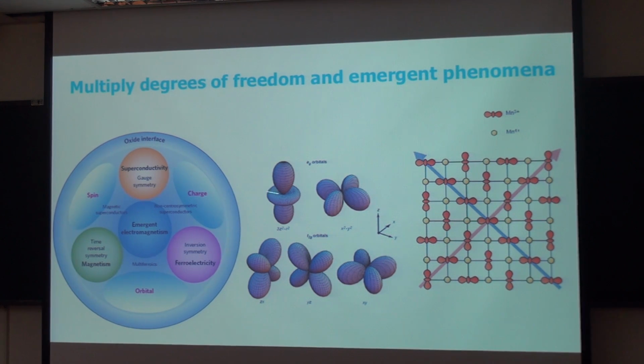But for the transition metal oxides, we can see the orbital degrees of freedom play a very important role. It is not only due to the anisotropic orbital shape of these d electrons, but also the multiple valence states, as well as its orbital occupation depends strongly on the crystal structure and couples in turn the spin degrees of freedom as well as the electronic properties. This figure demonstrates the orbital degrees of freedom with the so-called charge orbital order observed in the manganites.